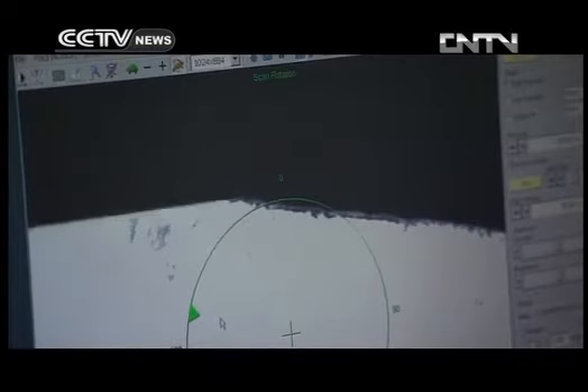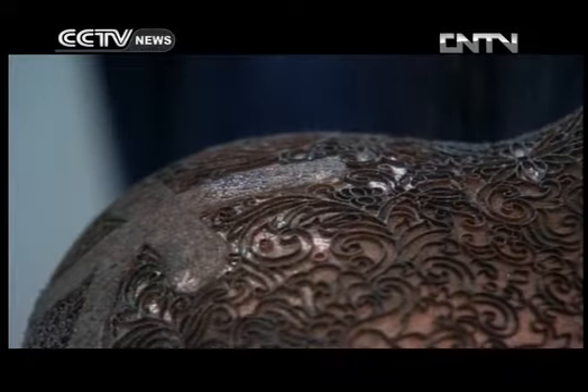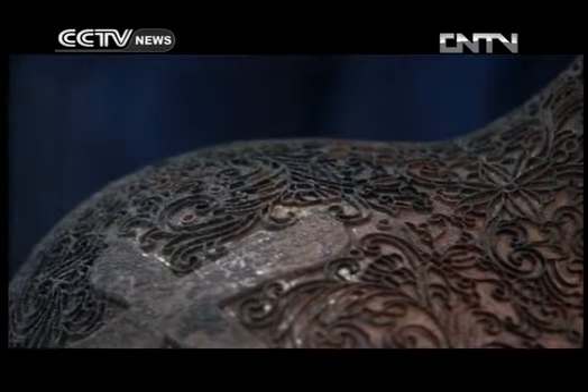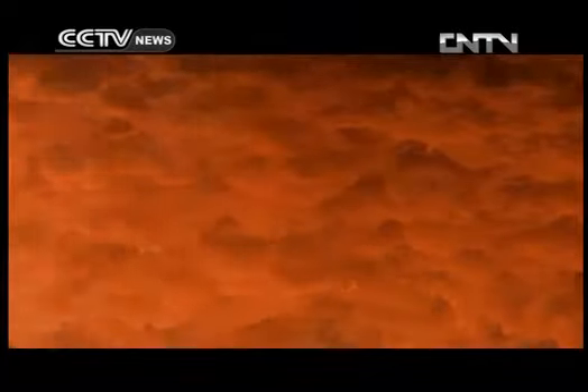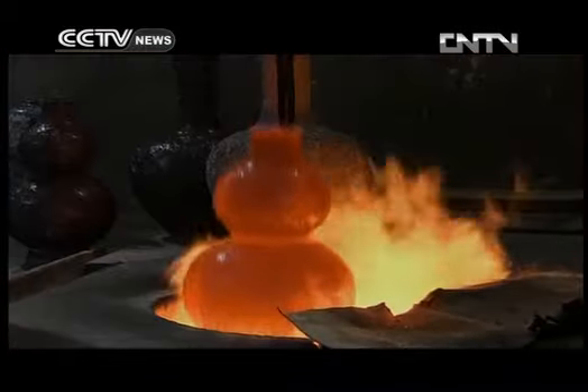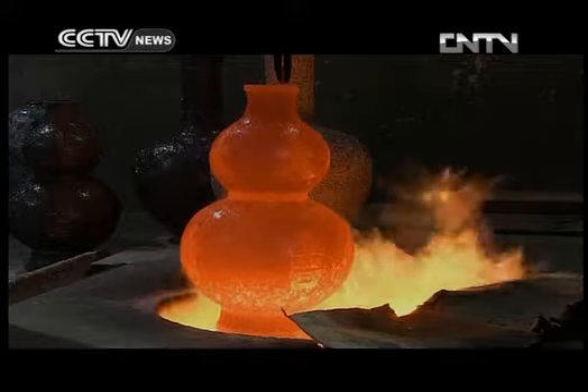An electron microscope reveals that the copper base and the filigree elements of the Qing dynasty cloisonne samples are made of pure copper. It also shows that the welding flux has a relatively high zinc content. With zinc present, a temperature of just 1000 degrees is needed for welding, or brazing, as this particular method is known.